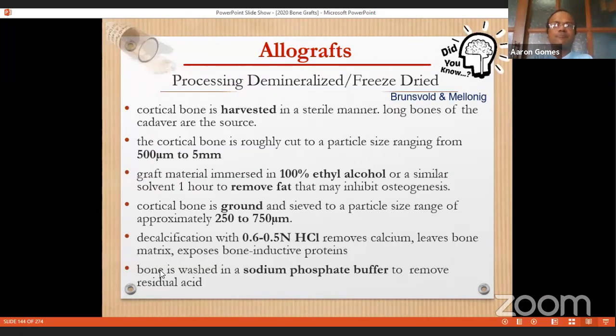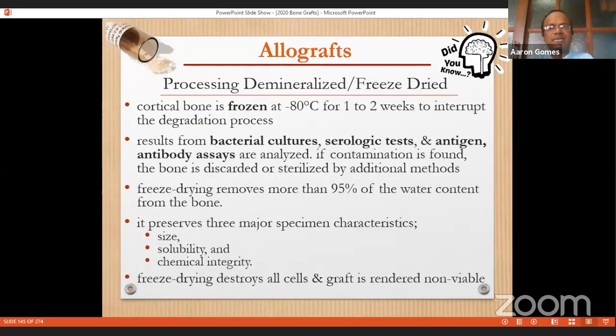Did you know about the processing of demineralized freeze-dried bone allograft? You take the harvesting of either cortical or cancellous bone from the cadaver, then it is roughly cut to a particle size of 500 microns to 5 mm. Then it is immersed in 100% ethyl alcohol to remove fat. It is further ground to 250 to 750 microns and then decalcified in 0.6 N hydrochloric acid. The excess residual acid is removed with a sodium phosphate buffer. Then it is frozen at minus 80 degrees centigrade for 1 to 2 weeks to interrupt the degradation process.